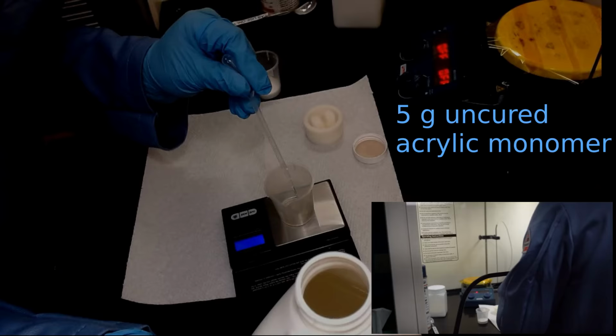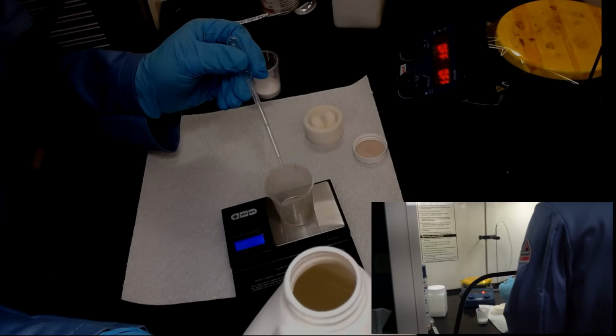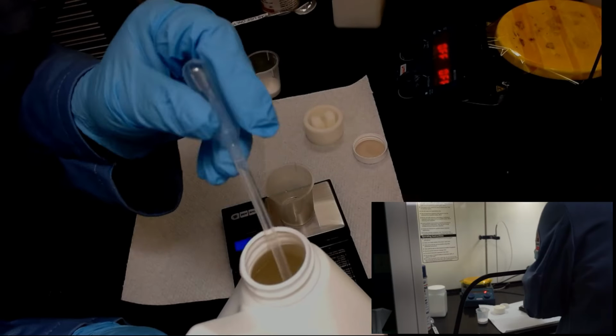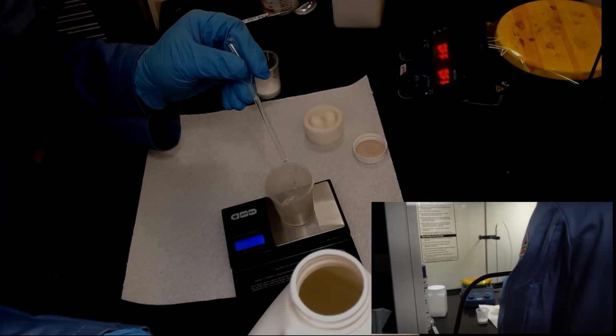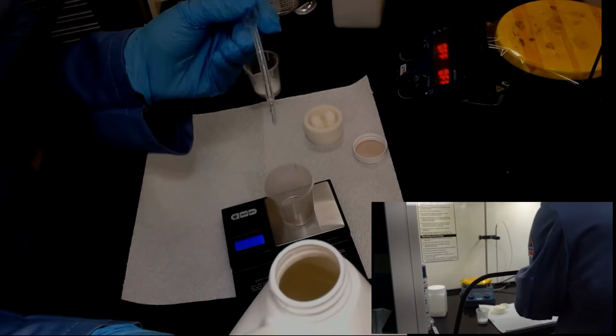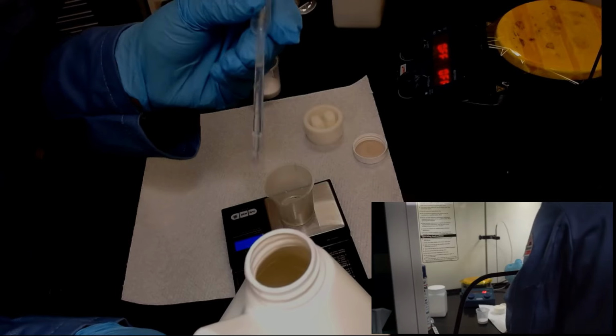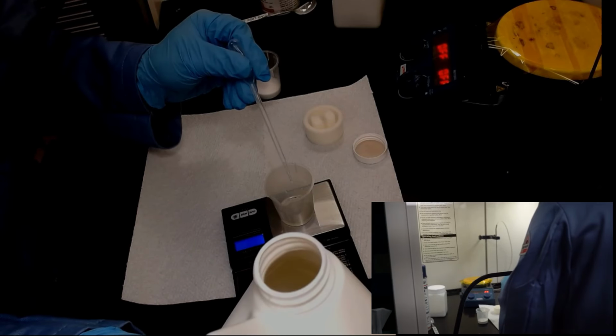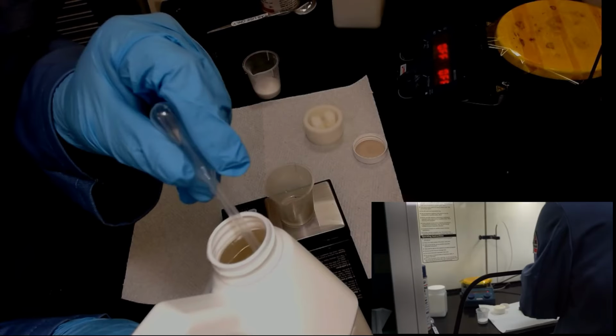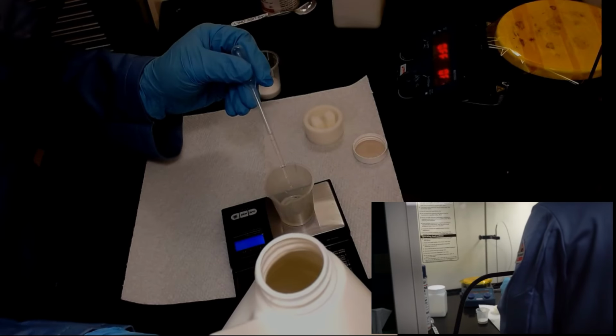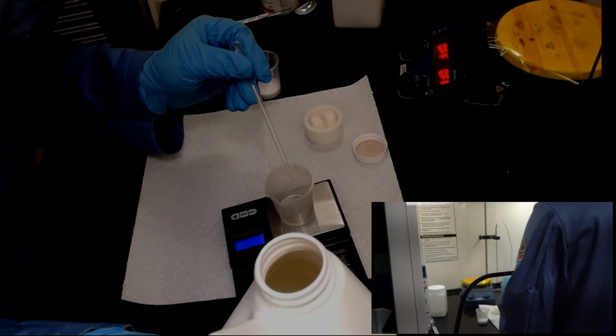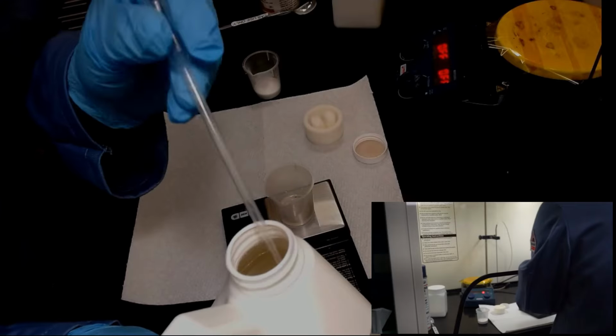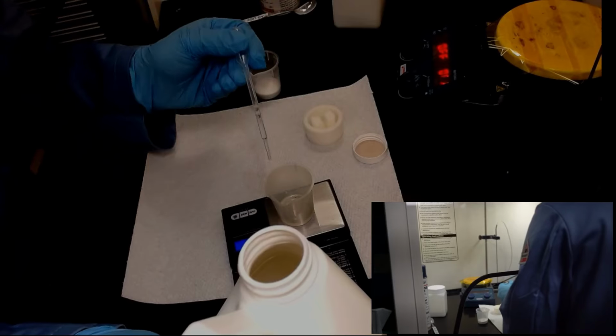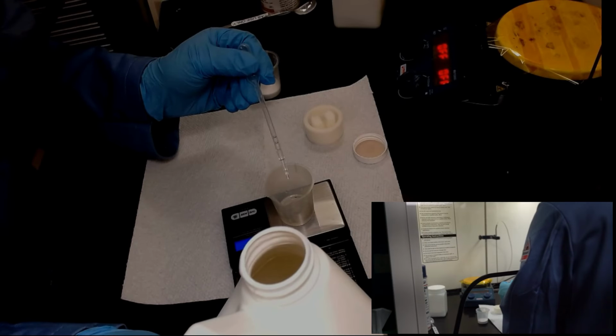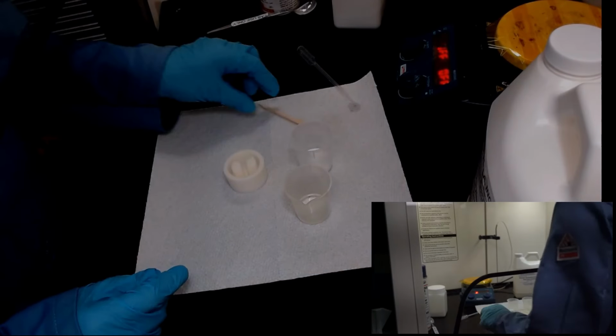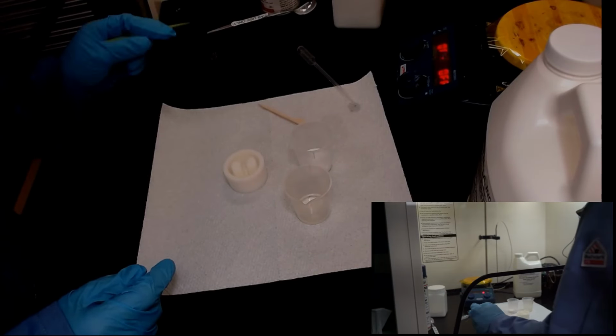So the way that this resin system works is that the powder is acrylic particulates plus, I believe, an organic peroxide-based curing additive, and then the liquid is additional uncured monomer. When they're mixed, you get a solid resin with the monomer cross-linking around the existing particulates. And one of the nice things about this system is that you have a pretty forgiving mix ratio. It's not like epoxy where if you get things a little bit off, it's not going to cure properly.